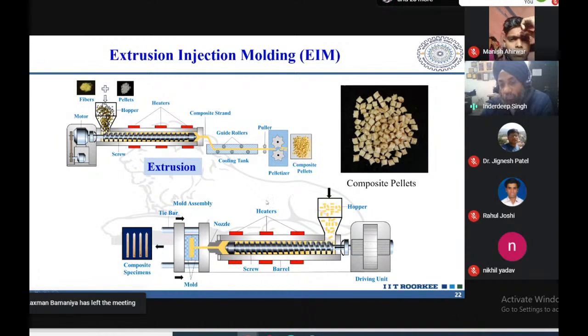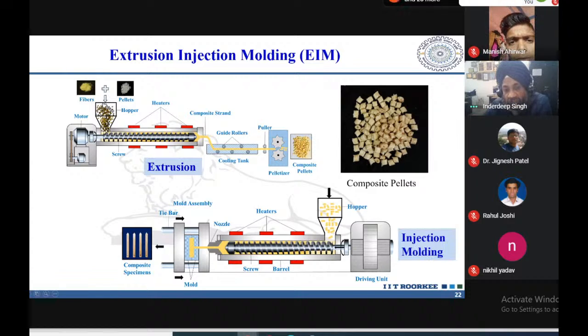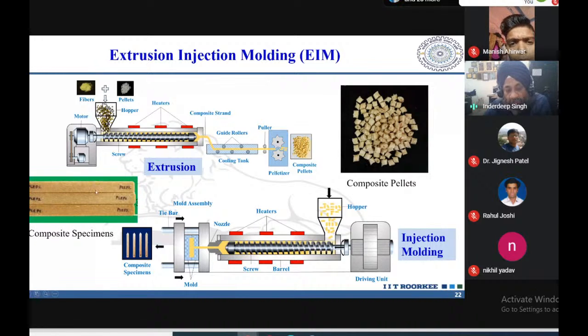But here, instead of putting the fiber and the polymer directly into the injection molding machine, we are putting it into the extruder, and first we are extruding a composite strand and pelletizing it to make the pellets, and these pellets are now being used as the raw material for the injection molding process. So here we are using two processes, extrusion and injection molding, and therefore we are calling it extrusion injection molding. And finally we are able to make the samples like this.